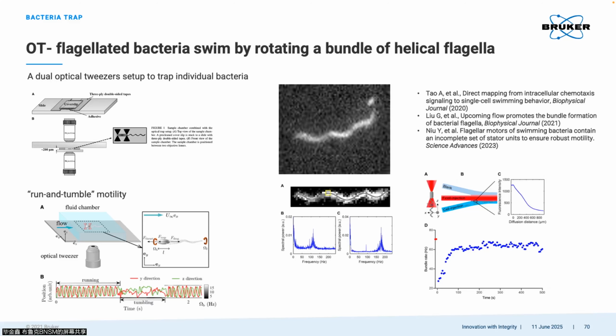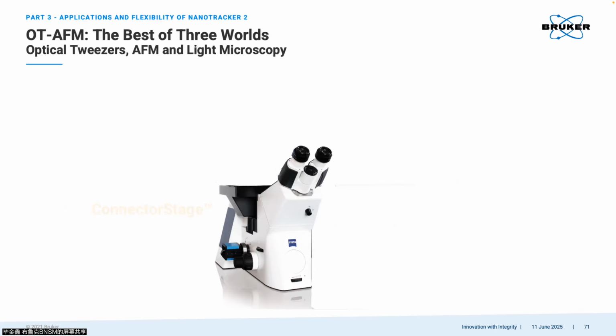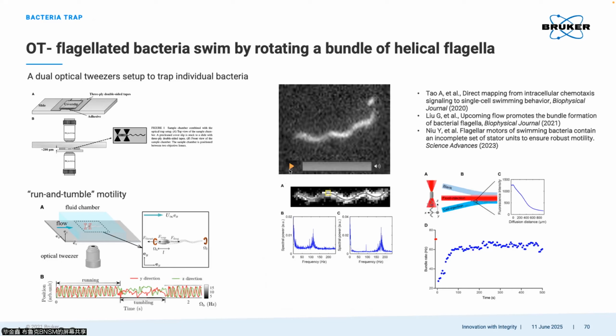So they apply 2 traps to trap the bacteria, and they use a high speed camera to monitor the motion of the flagella. They analyze, for example, this part, and see the power spectral signal. They can see the frequency of this rotation. And the whole purpose of establishing this system is that they use the optical tweezer to trap the bacteria and put the bacteria under different solutions. One may be only PBS solution, then they introduce a high concentration of some sugar, and they want to see at different viscosity what the motion of the flagella is. That's the whole experiment.